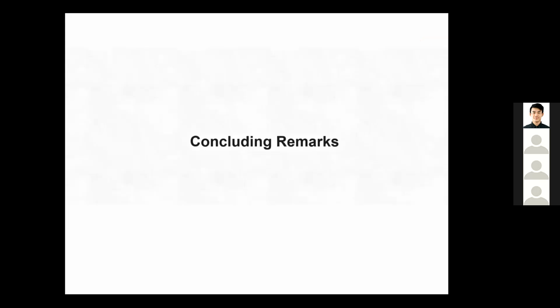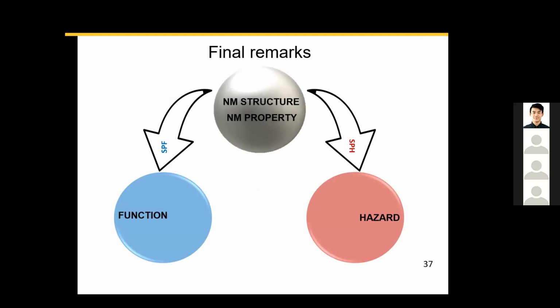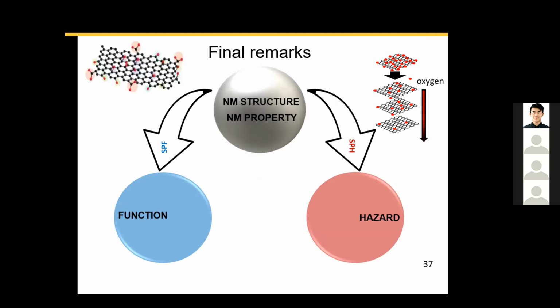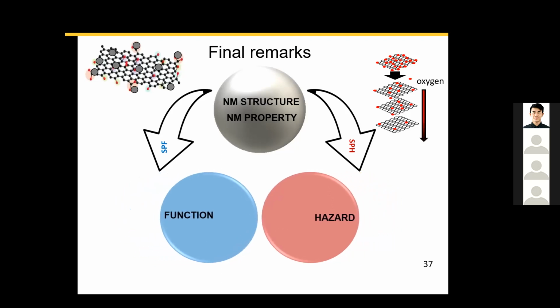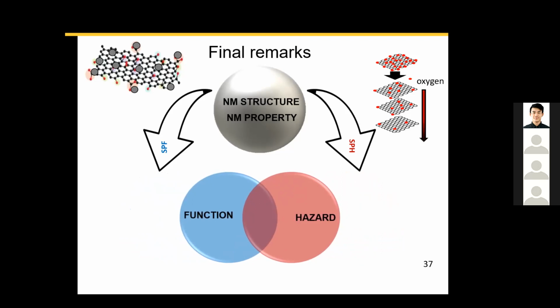So for the concluding remarks, I have shown you 3 different projects. The first one is where we tried to establish surface property hazard relationships. We have seen that as we change the surface chemistry of our materials, we have different interactions with bacteria. The other project tells us that if we create a graphene oxide composite and functionalize it with silver nanoparticles, we can increase the performance of these materials at removing a pollutant from water. And last but not least, we have shown a merged interaction between these relationships, where if we sulfidize silver nanoparticles on a reverse osmosis membrane, we can slow down the silver release while at the same time maintaining the antibacterial property that we want for biofouling control.